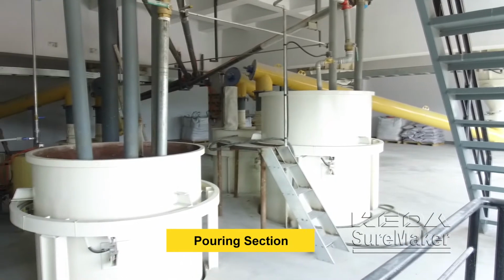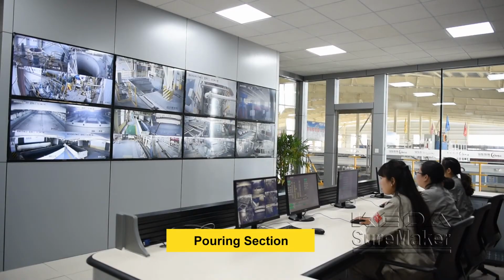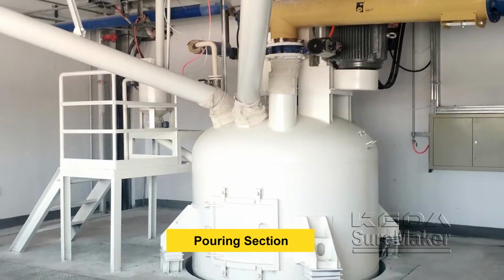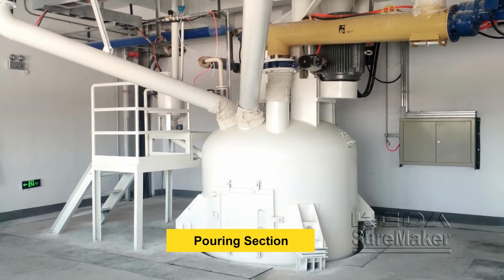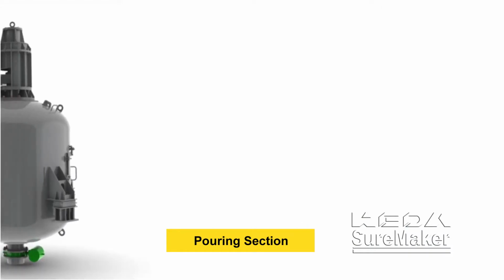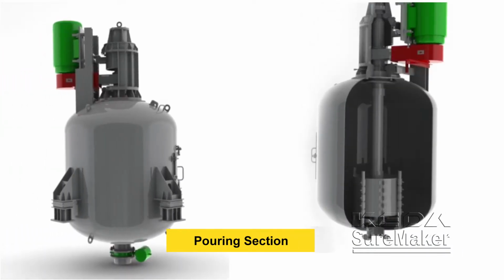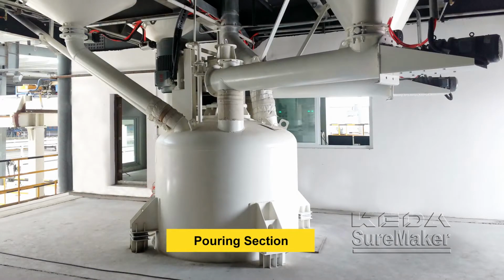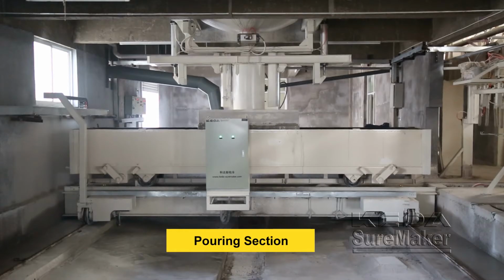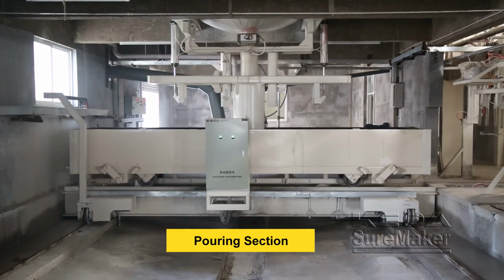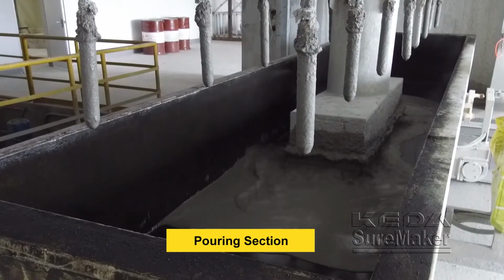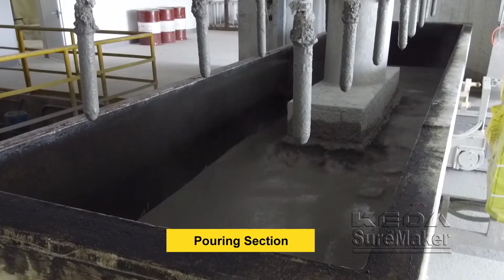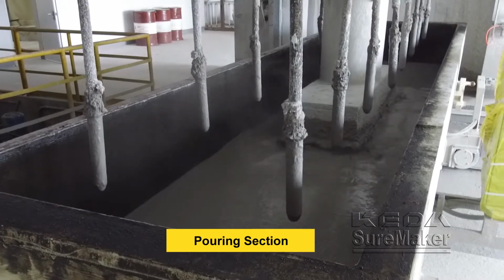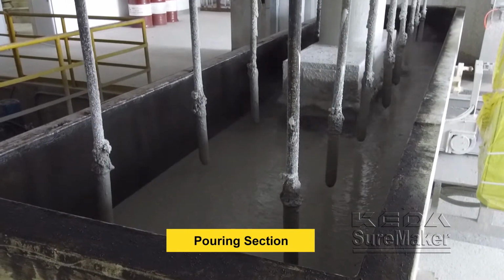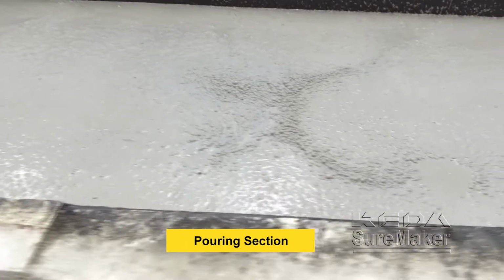The automatic batching control system ensures the accuracy and reliability of batching operation. With the structure of double-cross paddle and modular draft tube, the pouring mixer can mix the slurry for producing AAC with density from 300 kilograms per cubic meter to 700 kilograms per cubic meter. The lifting pouring head efficiently eliminates big bubbles and prevents the oil layer from being washed away. Bubble treatment machine ensures uniform distribution of bubbles in slurry.